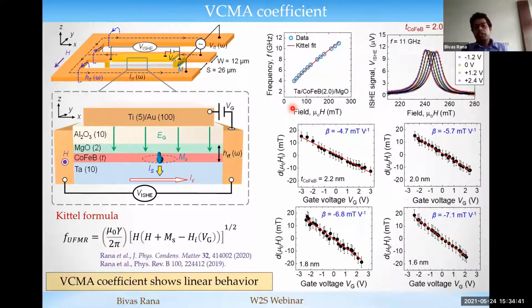So then, before exciting the spin wave, we tried to see how much of the anisotropy field we can modulate by the gate voltage in our system. The multilayer system we use is based on cobalt iron boron and MgO. Of course, as an underlayer, we have tantalum or tantalum ruthenium tantalum. Then we measure the ferromagnetic resonance of the system under the application of various gate voltages, so that we can tune the perpendicular anisotropy. And here is the typical signal which we measure. Here we plot the inverse spin Hall effect signal as a function of the bias magnetic field for various applied gate voltages. You can see the resonance field is varying as a function of the gate voltage due to the variation of perpendicular magnetic anisotropy.